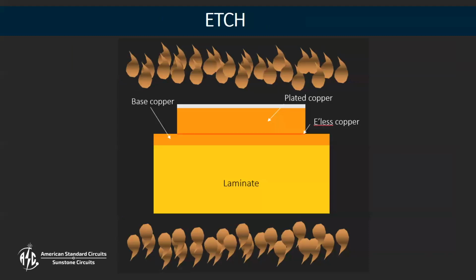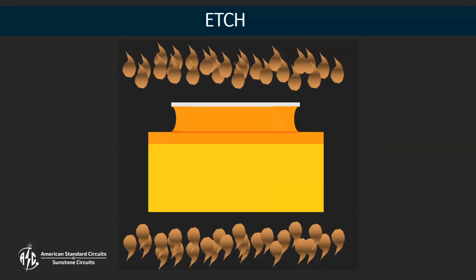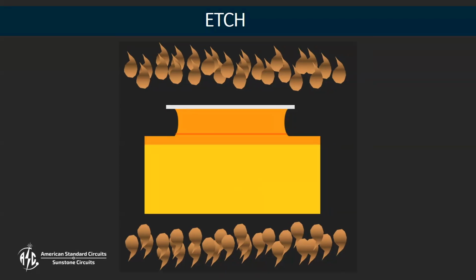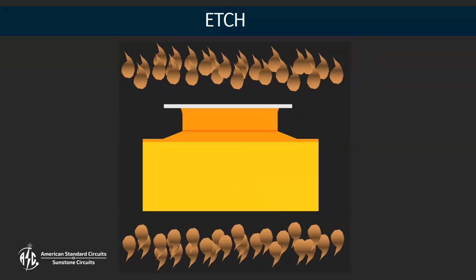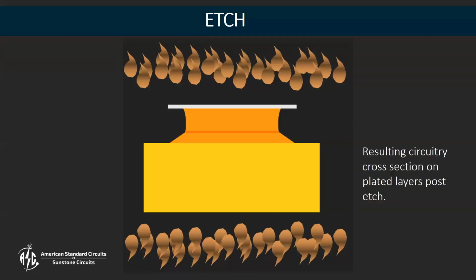The next step we do, so okay, here's kind of a cross-section view of what we see. There's our laminate, our base copper, our thin layer of electroless copper, and then our plated copper with the tin on top of it. After it goes through etch, you can kind of see the sidewalls have that curved, trapezoidal look to them, which is the effect of the etching. The thicker the copper layer, the more pronounced this undercut of the etch resist is. So you can see as we increase that copper thickness, we change the shape and the size of that trace.